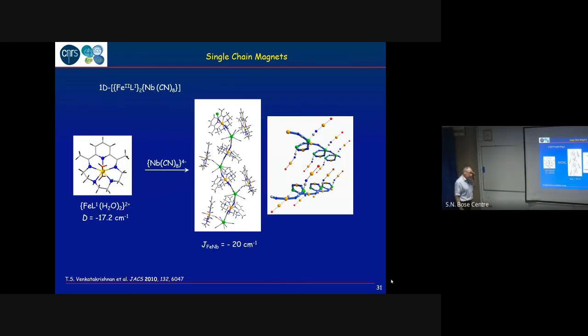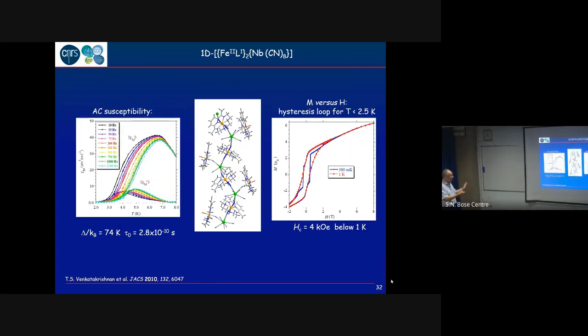So this is one of the very first single chain magnets we have obtained. This compound was made with an iron complex that was used to introduce the magnetic anisotropy, and here we use niobium cyanide as linker, and what we get is a chain compound. Here is a simplified view of the same. So this is just the direction of the chain, and on the side of the chain we have again some terminal ions. For this compound, we have quite large exchange interaction. So this is what we wanted, and of course we have also the slow relaxation because we have anisotropy.